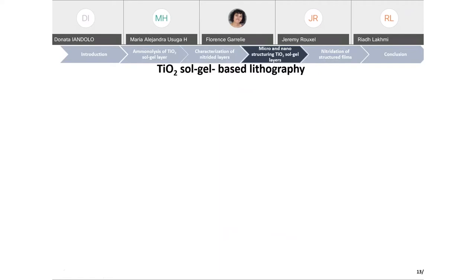How does the photosensitive sol-gel work? Using the photolithography method, at first we realize the deposition of sol-gel using spin or dip coating. A thermal treatment at low temperature was made to keep the photosensitive behavior of the sol-gel. When we realize the UV illumination,